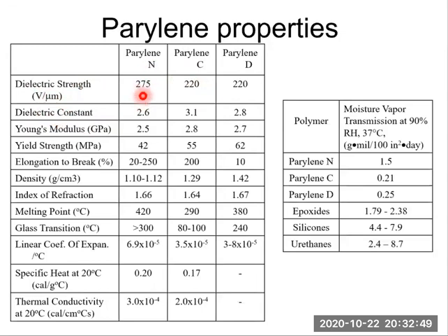Dielectric constant, parylene N 2.6, parylene C 3.1, parylene D 2.8. Young's modulus, somewhere between 2 and 3 GPa, gigapascal. And polysilicon has a Young's modulus of 160 GPa. So we can see parylene has a much smaller Young's modulus. That's typical for polymer. Elongation to break, parylene C, 200%. Index of refraction, 1.66, 1.64, 1.67. All three members have a similar index of refraction.